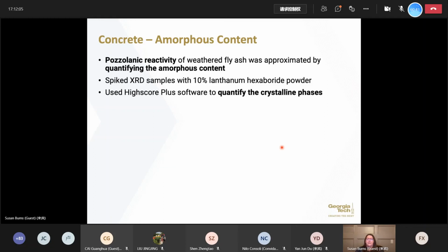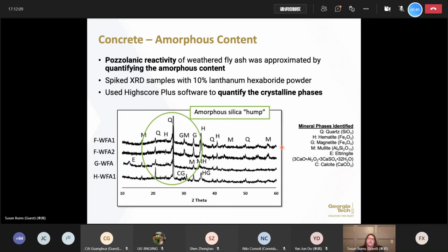At the end of the day, we want to use fly ash as a substitute for cement, right? So in this case, we have to be concerned about the amorphous content. Do we have enough amorphous phase here to actually use this as a cement replacement? And what you can see is that we've got this characteristic amorphous silica hump. So that gave us confidence that we can use these aged, weathered materials in our concrete.